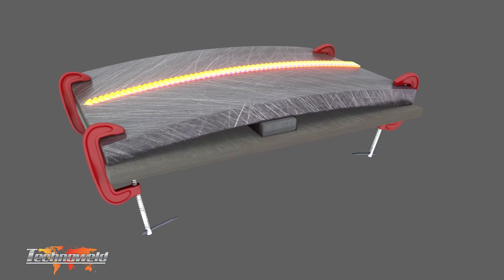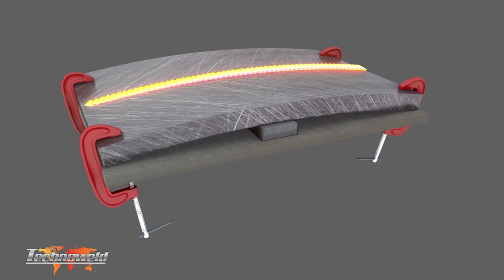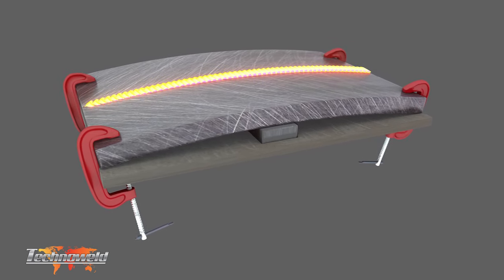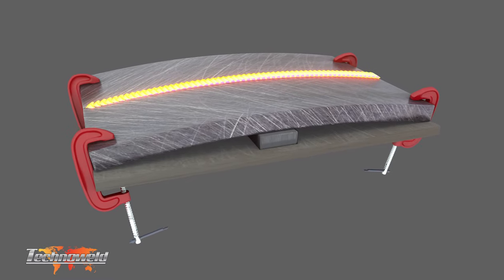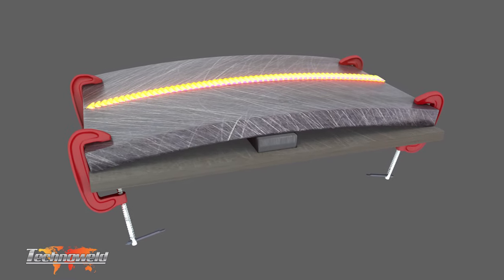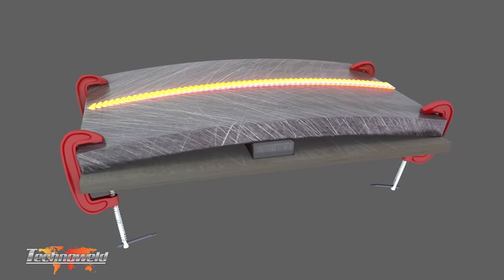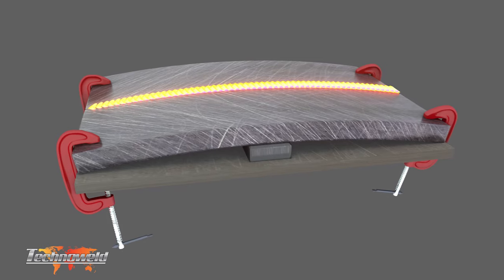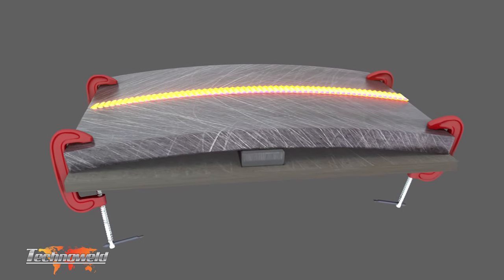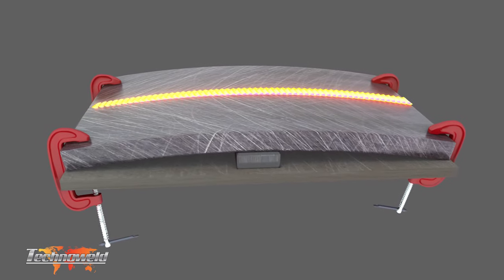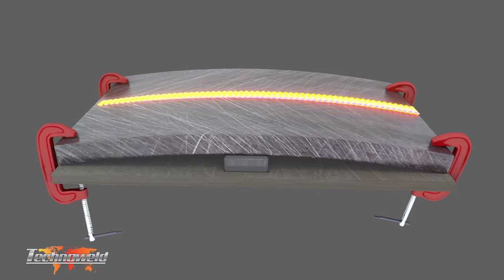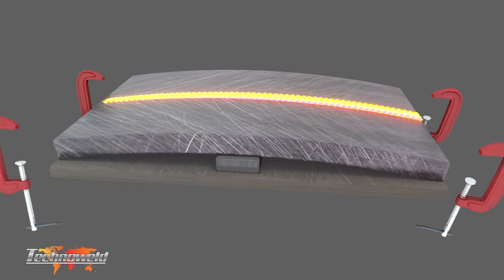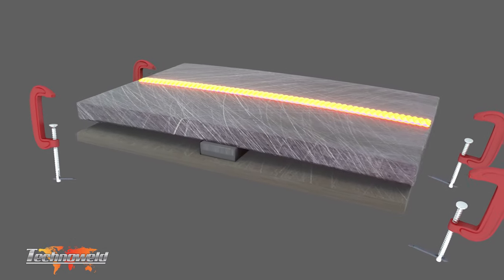When understanding distortion and the effect it can have on the job, we can apply tension or pre-camber the material to compensate. We have tensioned the welded joint using clamps, fixing them in the opposing direction of the weld. Once the weld is completed, if we release the clamps, the shrinkage forces will pull the plate back into shape as it cools.